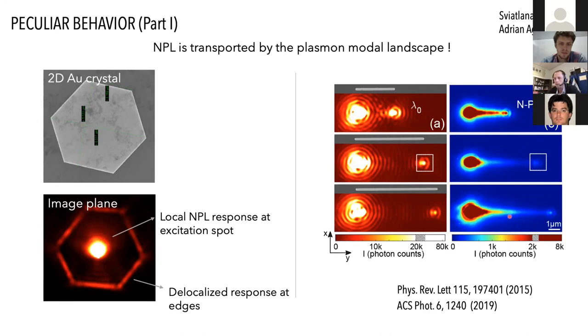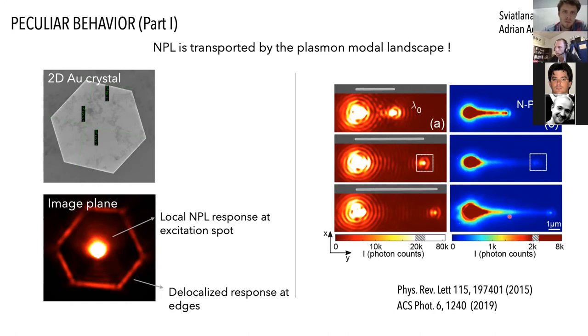Well, it's a good question. It's a little bit more complex than what I'm trying to convey here. Of course, you excite surface plasmon at all these frequencies because it's a local source. At the end of the day, it's very local, so you will have the conditions to excite a surface plasmon polariton at all the wavelengths. However, as I said before, the conversion efficiency of the process is very small. We're talking about 10 to the minus 10, sorry. So all the plasmons that will be excited at these NPL wavelengths will be way dimmer than the plasmon at the fundamental frequency, which is creating most of the signal. So yes, you have this, but this is a negligible portion of the story. Thank you, I understand, yes.